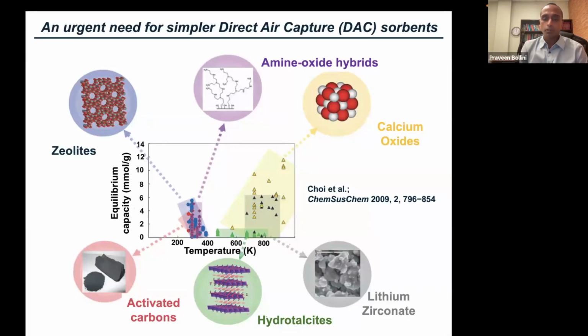So if we look at a map of the different types of materials that have been evaluated for direct air capture, I'm excluding MOFs here because of their limited stability. But what's plotted is the equilibrium capacity at about 0.1 bar CO2. So this is for flue gas applications as a function of the temperature at which these materials operate. And generally speaking, each of these materials has one limitation or another that prevents their commercial implementation.